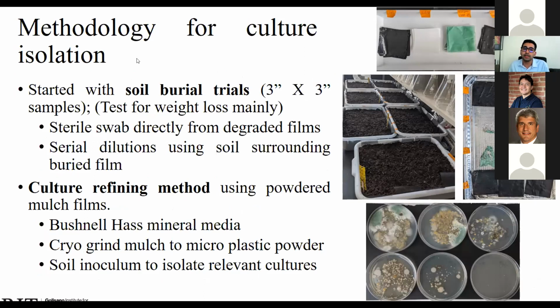So we started initially with burying our samples, and by burying I mean we cut the plastic film samples in sizes of 3 by 3 inches, and we buried them in soil bins as shown. And at regular time intervals, we took these out, and over time, as we saw some biodegradation, we were able to take weight loss as a direct measure for biodegradation. And based on this, we were able to isolate specific microbes.